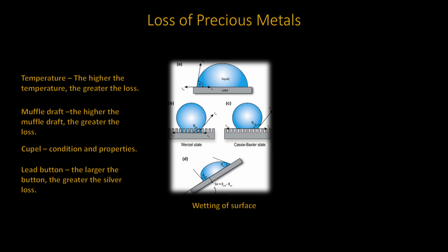Most of the losses will be in regards to the silver. Larger button size requires a longer cupellation time. This allows for the oxidation of some of the silver, which in turn will be absorbed by the cupel. Any impurities in the button will also require a longer cupellation time, as well as an increase in temperature. Those impurities will need to be oxidized and absorbed. Loss of silver will also increase. Some gold and PGM group metals, if any, may be lost.